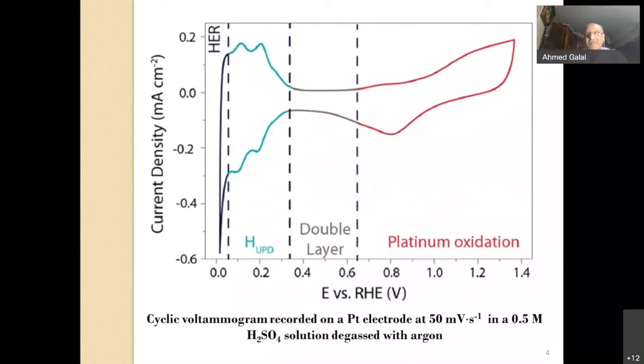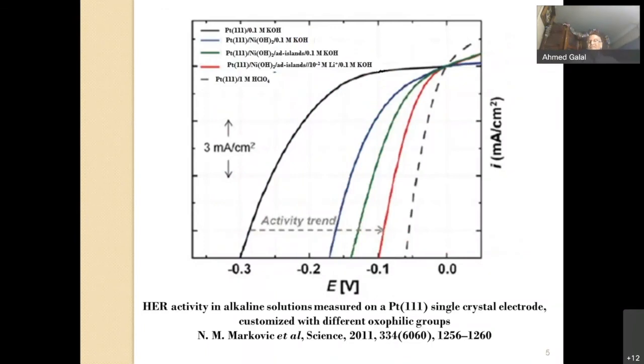Here is the very famous cyclic voltammogram that is being performed on a polycrystalline platinum electrode in an acid medium, and four regions are being identified: the platinum oxidation forming platinum oxide and oxyhydroxides, and the double layer region where no Faradaic activity is being observed, and then this large envelope for the hydrogen underpotential deposition, and then we have the fourth region for the hydrogen evolution reaction. This is the most important region here, where everybody is looking.